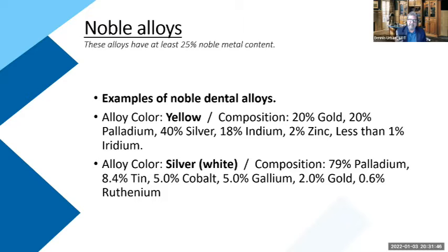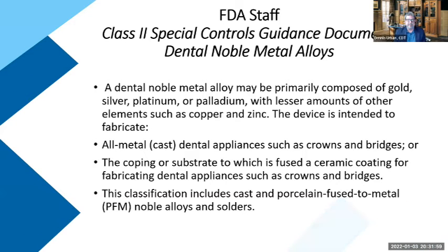One of the things we had problems with in the past, like I mentioned earlier, was silver palladium. That silver had an effect on our crown, so we really had to adjust what alloy we were utilizing for a specific porcelain. According to the FDA's Class 2 Special Controls Guidance Document on dental metal alloys, they may be primarily composed of gold, silver, platinum, or palladium, with lesser amounts of other elements such as copper and zinc. They're for crowns and bridges, copings or substrate to which a fused ceramic coating is applied. The classification includes cast and porcelain fused to metal noble alloys and specific solders for each one.